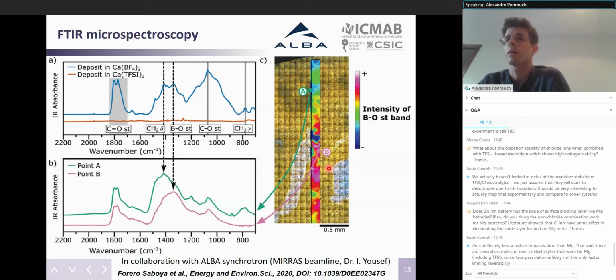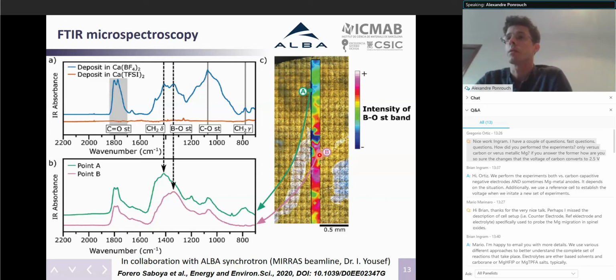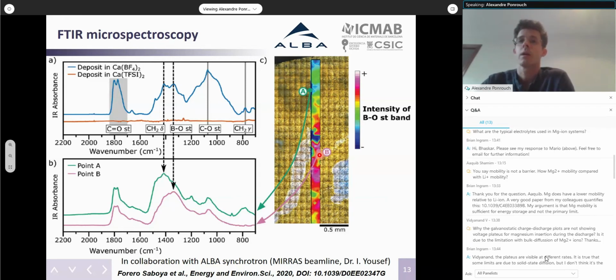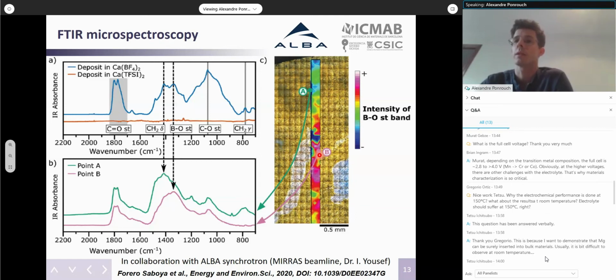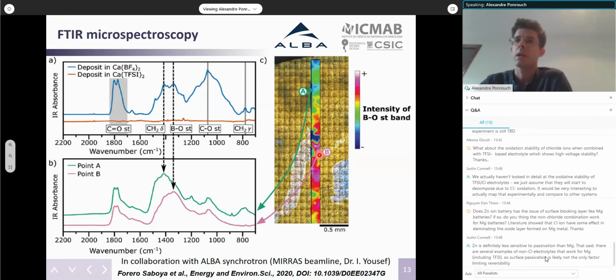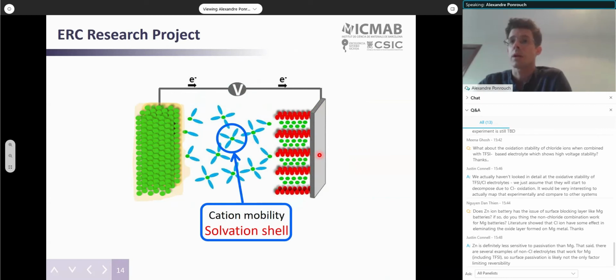So you have an intensity, a color scale that is proportional to the amount of borates in the passivation layer. You can clearly see that these borates are not uniformly distributed on the surface. If this is the conducting species, this is definitely something we have to improve to improve the plating stripping kinetics. So moving now to the electrolytes.